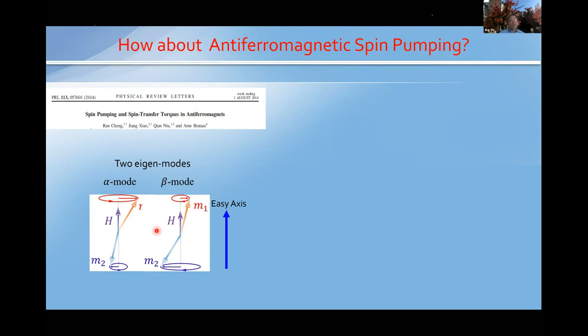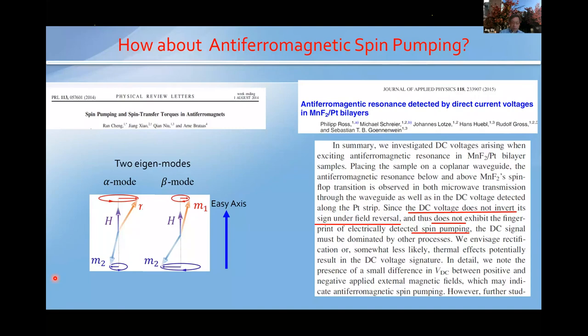Because of this, again, this familiar picture, there are two eigen states. So one can actually selectively excite one of the two modes. But you can actually go through the resonance and detect it. The goal is to detect electrically, right? The first attempt was made by Goennenwein's group, published in 2015. For the electrical detection, they concluded that there might be some rectification effect and also the heating effect due to Seebeck, a spurious signal mixed in the resonance signal. The real inverse spin Hall signal is probably less than 10%, according to this report.